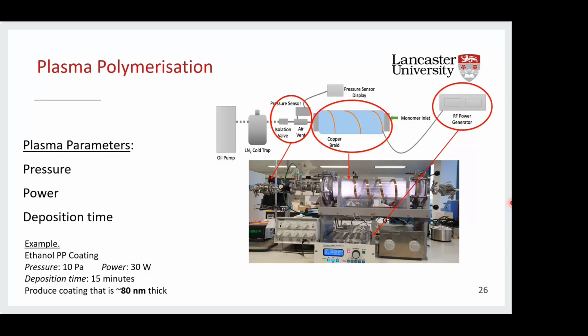So just as an example, an ethanol plasma polymer coating that I've produced at 10 pascals with 30 watts of power and approximately 15-minute deposition time gives a coating of around 80 nanometers. I should also briefly state that all of the plasma work that we do tends to use continuous wave plasma, but you can have the option to use pulsed plasma using this oscillator in this picture here.